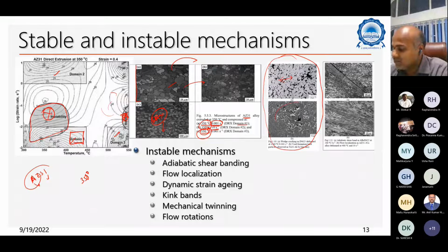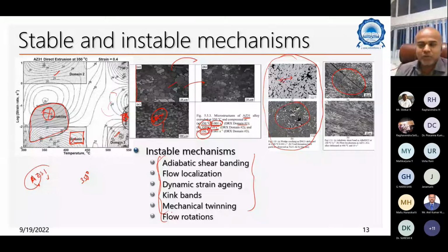So there are regions where the material has certain pores or certain wedge cracking or certain adiabatic shear bands or certain flow localizations. So the initial processing of the material is not good. When I say processing, it could be wrought processing or it could be cast processing. And then you have to change the entire batch. Otherwise, it can no longer sustain. So these are all the undesirable mechanisms you want to avoid whenever you process it. That is the reason you have to optimize the temperature and time space